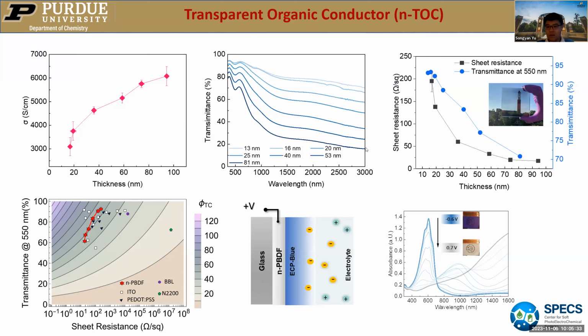Can I continue? I think it was somebody who was just logging in. Okay, keep going. Okay, sorry. So it has very good sheet resistance, and we can say from this figure that compared to other materials, even ITO, it has comparable performance. We also used this as the conducting polymer to replace ITO to build an electrochromic device. We have n-PBDF as a conductor layer and a chromic polymer, and we use it in electrolyte. It shows very good performance because it is both conductive and transparent.